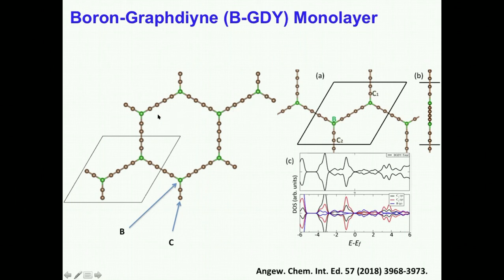But the thing is, in a pure form, if we use it as a hydrogen storage, the hydrogen interacts with this material very weakly. As we discussed in the previous slide, the bonding should be appropriate. The bonding of hydrogen with the host material should not be very strong and should not be very weak. So there should be some intermediate range for that bonding. And that intermediate range is 0.15 eV to 0.60 eV. I should have written that somewhere, sorry. Forgot that. So which means in the pure form, this is not good for hydrogen storage.